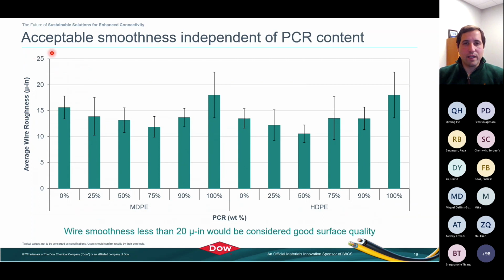And lastly, similar, we have the smoothness. So we looked again at the extrusion performance and the final wire or cable surface smoothness, again looking for less than about 20. In this case, all of them were very good as far as being able to produce a cable with a smooth surface at typical polyethylene jacket processing conditions. Nothing special about how the materials were processed. Basically, a drop into a standard processing condition and setup.